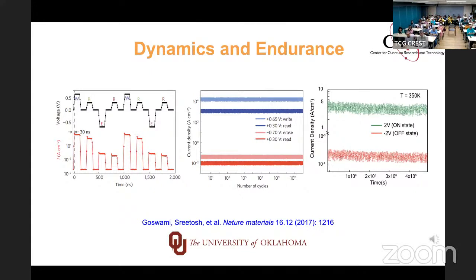Here, we have taken the device, heated it to 80 degrees centigrade, and just kept it in the on state and the off state. And you see these states are stable for like 3 months, basically, with nothing happening to them. Really amazingly stable system. So I got very excited.